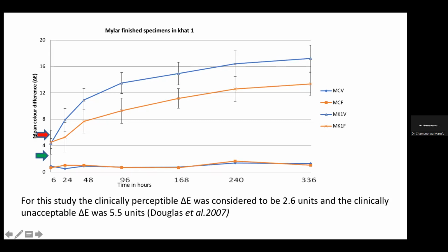And the red mark above, the red arrow on top, is the acceptability tolerance, which is 5.5 units from this study. So Douglas actually performed this study on dentists. And so these marks are points at which, for instance, the perceptibility mark is the point at which 50% of the dentists in the sample study could discern that there is a color change. And then the top part, which is the red mark, is the point at which 50% of the dentist sample would recommend that the restoration be changed. After that point, the discoloration was not acceptable.